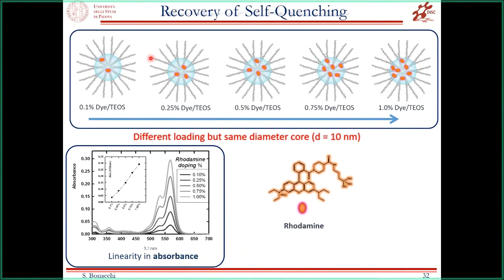And to check this, we synthesized this family of nanoparticles with the same size, the same core and the same shell, doped with an increasing amount of rhodamine dyes that we use as a probe because its photophysical properties are well known. And as you look at the absorption of this family of silica nanoparticles, you can clearly see an increase of absorbance, a sort of linear increase as a function of the doping, a loading effect.